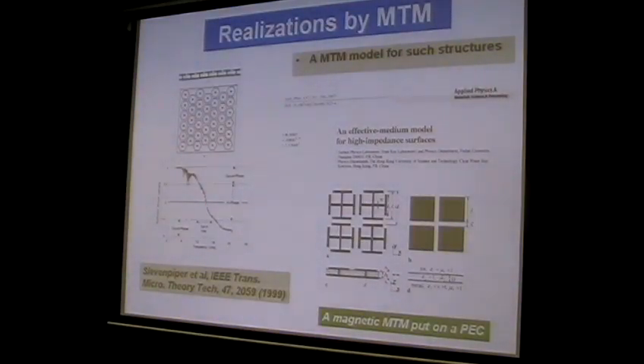They call this system high impedance surfaces. In recent years, we found that we can characterize this very complex high impedance surface by a magnetic material model. This kind of system can be described by a double layer effective media model, which is a metamaterial magnetic layer put onto a perfect conductor layer. So basically, we can design a metamaterial which can possess an arbitrary value of reflection phase.